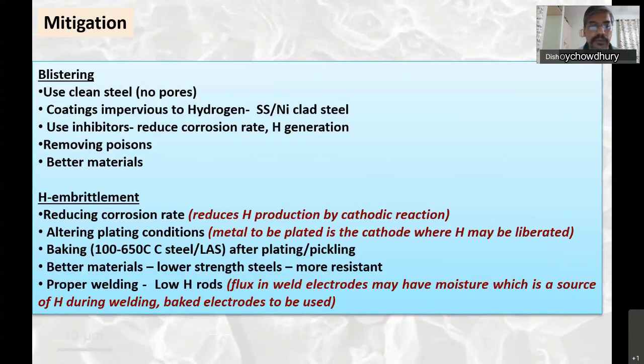If hydrogen is picked up, you can always bake it out in a temperature range of around 100 to 650. If the hydrogen comes out, then again you restore the original ductility of the material. Lower strength materials are better. As I said, during welding one has to take utmost care that welding electrodes are completely dry. The welding electrodes have to be baked nicely before welding. They should be removed from the baking furnace immediately before welding and taken directly for welding after retrieving from the furnace, so that there is no chance of moisture pickup.